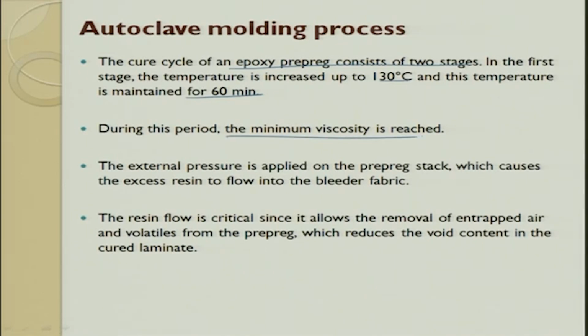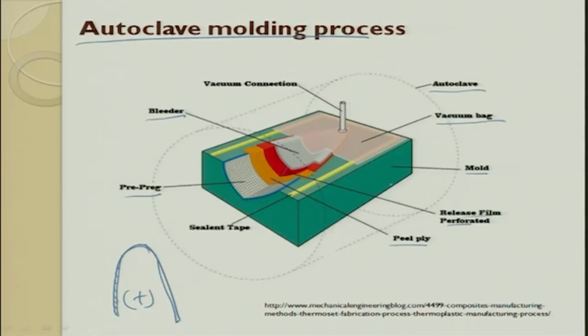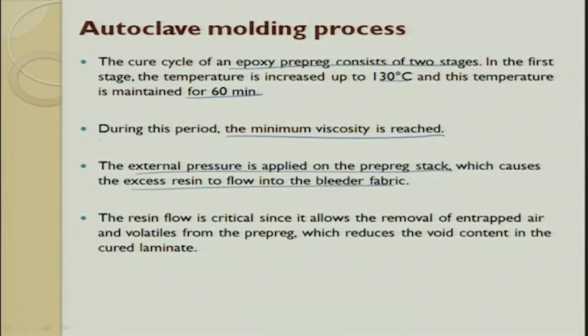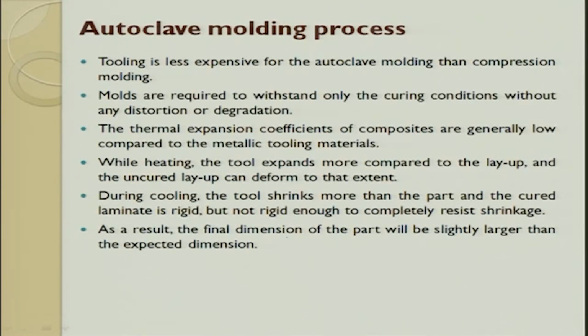During this period, the minimum viscosity is reached. The external pressure is applied on the prepreg stack, so that the excess resin flows into the bleeder fabric. So what is a bleeder fabric? You see here, here is a bleeder. It is like cotton which absorbs blood from a wound. Cotton is used in the same way. The resin flow is critical since it allows removal of the entrapped and volatile material from the prepreg.